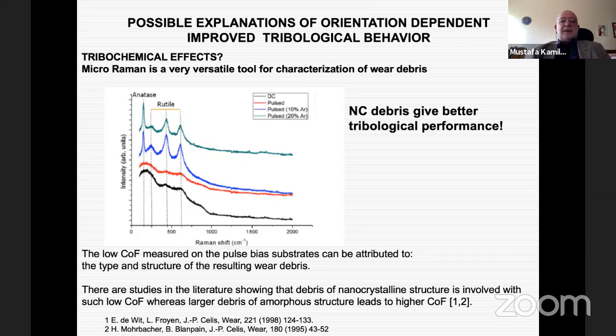So why? What happens when the surface is 1-1-1 oriented or 2-2-0 oriented? How may the debris character change? From the literature we can also see that debris in an amorphous structure leads to higher coefficients of friction. On the other hand, when the debris are nanocrystalline, we get much better tribological properties. So we end up with the conclusion that nanocrystalline debris give better performance with respect to tribological behavior.